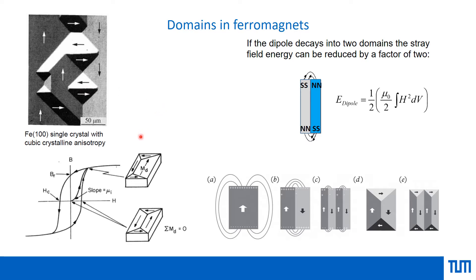For this iron crystal, the demagnetization field sums to zero because of the specific combination of domain structure present. Looking at the hysteresis loop, characteristic of a ferromagnet, if you start from zero field in a Landau-type configuration where the total magnetization is zero, applying a field causes domains aligned with the field direction — being energetically more favorable — to grow while others decay.